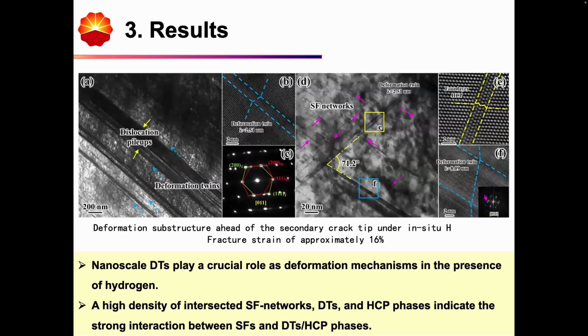Then we extracted the localized substructures ahead of the secondary crack tip for the in situ charging method, and the fracture strain is about 16%. First, because as hydrogen enters the materials, it will sharply decrease the stacking fault energy and promote the formation of deformation twins.